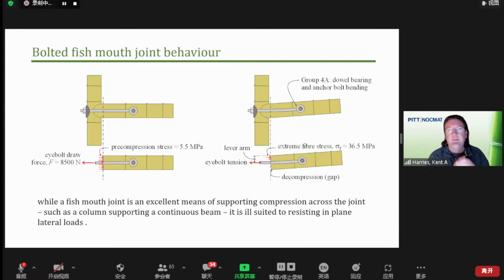Just then, sort of as some observations, I wanted to look at this particular test and the bolted fish mouth that we did test. After all, we have 40 data points and we may as well look at them. So our test setup, we actually pre-compressed or used the eye bolt to draw a fairly large force, 8,500 newtons. This was determined using a torque wrench. And so if I look at the compression force in the beam element, that's about 5.5 MPa if we take our average values.